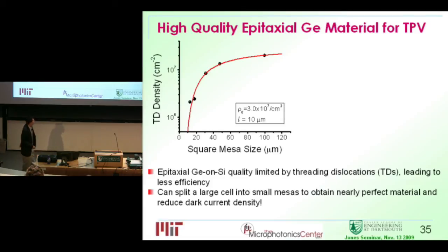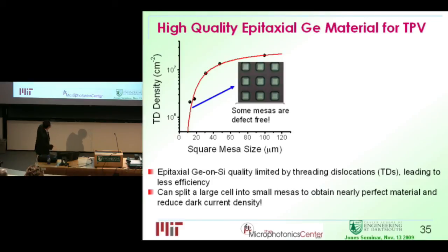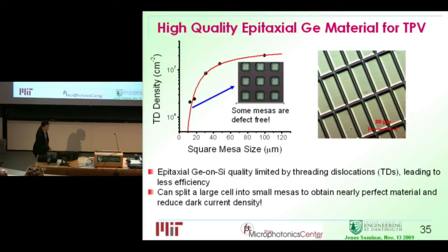So one problem with germanium on silicon is that it tends to have a lot of defects due to this lattice mismatch. Germanium has a larger lattice, silicon has a smaller lattice. You grow one upon the other, then you tend to generate misfit dislocations. One way we found to deal with that is to grow germanium on really small areas. You can get a really perfect piece of germanium without any defect. So instead of making a large germanium silicon cell, we're actually dividing those into small areas, just like an insect's eye, so that we can get more perfect crystal material. And even with the fabrication of this outside layer, we can still achieve much higher performance in terms of dollar per watt for these devices.